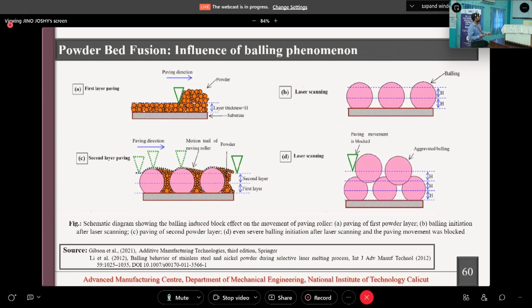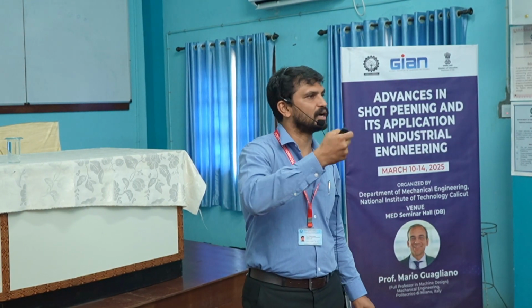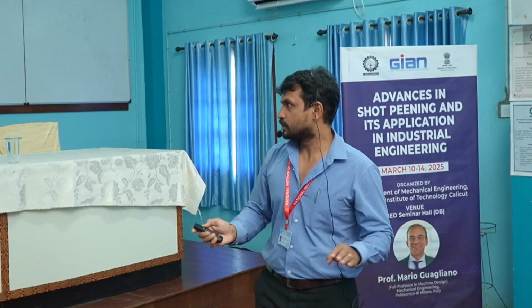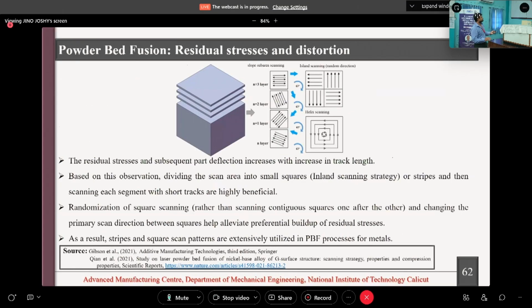Okay, it will be going up and down. In this case there is no problem, it is only going up and down. But if it ends up in the worse condition, the process will be stopped in between. The laser recoater blade will be stopped by the balls, and the process will stop there. Okay, so this is the balling phenomenon and the energy correlations, and finally the residual stress distributions.